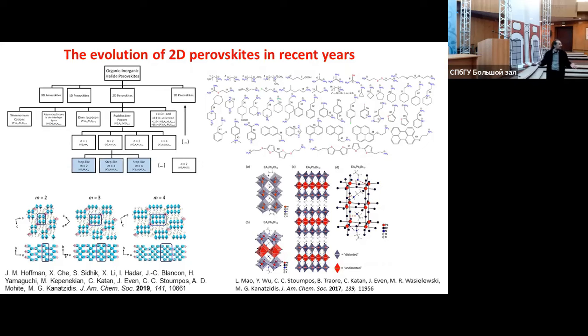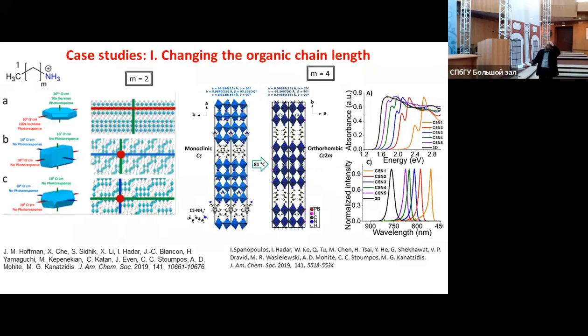So one example of what we can play with is the length of the chain. You would imagine in a quantum well, you want to adjust the properties by tuning the length of the well and the barrier. In this case, if you go too small, and going too small is important because we want to have electronic communication between the layers, what happens is you break the structure. But if you go too large, by increasing the carbon atoms in the carbon chain, basically what you see is exactly the same effect.